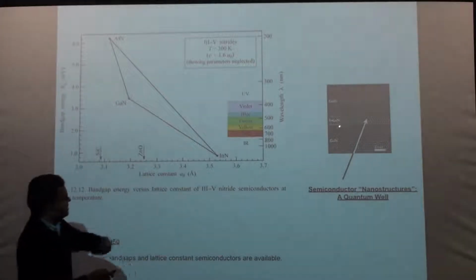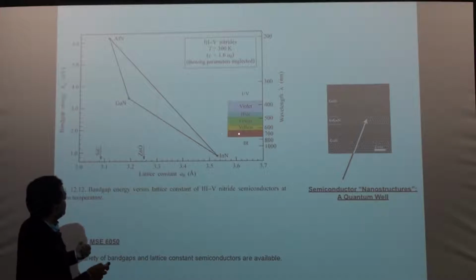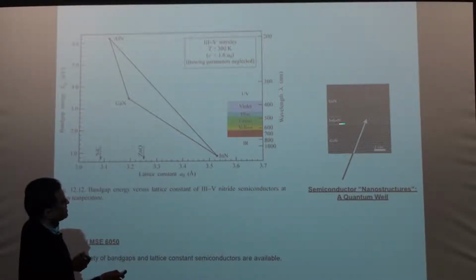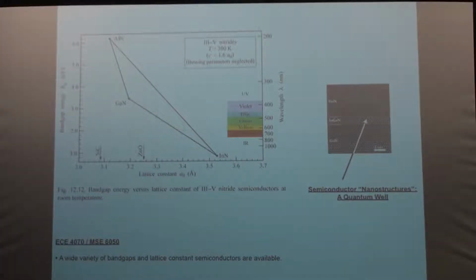For example, if you grow indium gallium nitride on gallium nitride, let's say you add about 10 or 15% of indium to gallium. And here's a layer that's grown, which is very thin. I know it's not very easily seen, but it's a few nanometers of indium gallium nitride. So that would be a quantum well inside gallium nitride, which has a larger band gap. If you are able to put electrons and holes into this layer, it is going to emit light of blue color. So you design this out, and it emits light of blue color, and that's what is used today for all the LEDs.